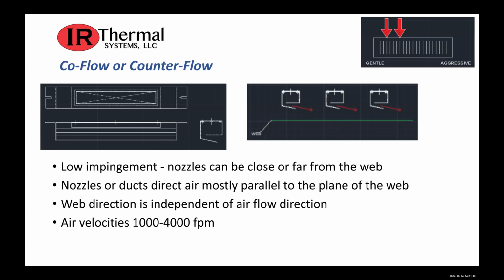The next step up from there would be a co-flow or counterflow zone. This can be controlled by a zone where you're delivering air on one side and taking it out on the other, or on an air bar to air bar basis, which is shown in the picture in the middle to the right. This type of zone has low impingement, and the nozzles can be close or far from the web. The nozzles or ducts direct the air mostly in the parallel plane of the web, and the web direction is independent of the airflow direction. Common air velocities for this are from 1,000 to 4,000 feet per minute.